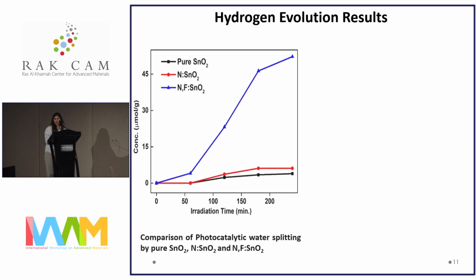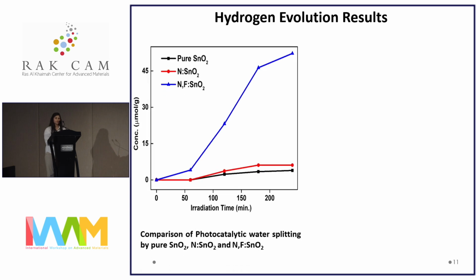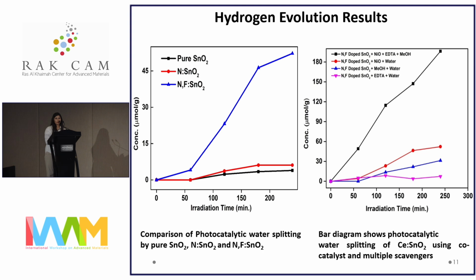Coming on to the results, the hydrogen evolution results were compared with pure SnO2 and with nitrogen-doped SnO2, and we can see from the graph that the hydrogen evolution rate was higher in the case of nitrogen-fluorine SnO2. Then, to further enhance the efficiency of hydrogen evolution, we performed trial experiments with some scavengers, sacrificial agents and co-catalysts, and it was found that using a combination of EDTA and methanol as a scavenger and in the presence of nickel oxide, nitrogen-fluorine co-doped SnO2 was giving a 196.2 micromole per gram per hour hydrogen evolution rate.